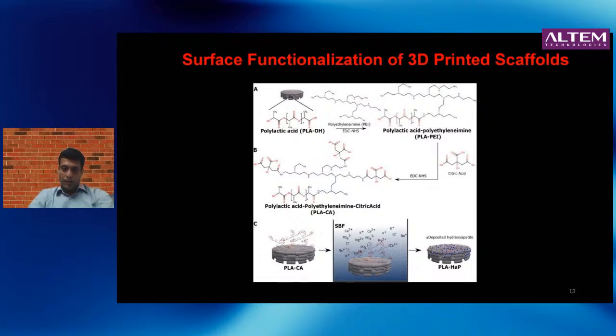So what we did is basically start with this polylactic acid. This was dipped in sodium hydroxide solution so that you can actually generate some OH groups on the surface. And then we conjugated low molecular weight polyethyleneimine to it. And what that did was to essentially put some amine groups on the surface of the polylactic acid. And on top of it, we conjugated citric acid. The amine and the citric acid groups were conjugated, so that now you had a surface that was decorated with citric acid.